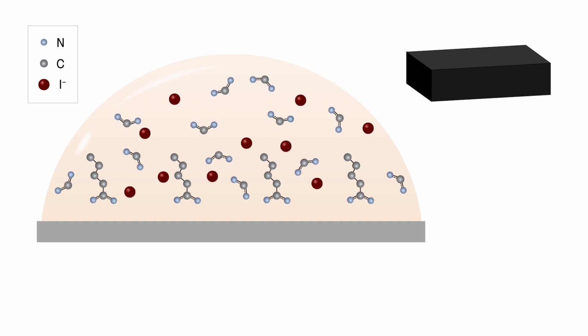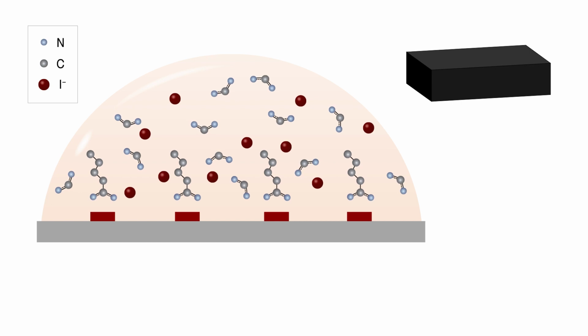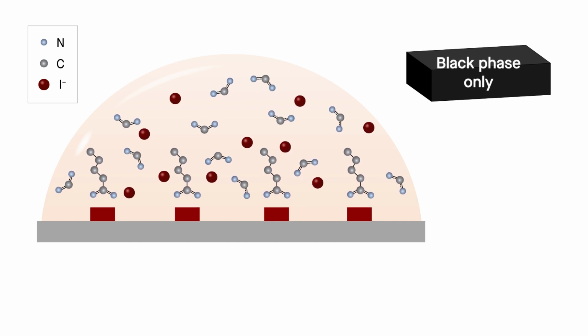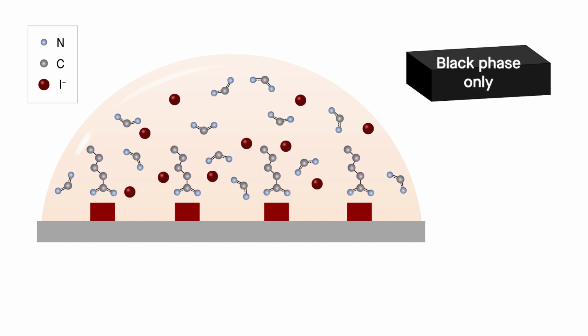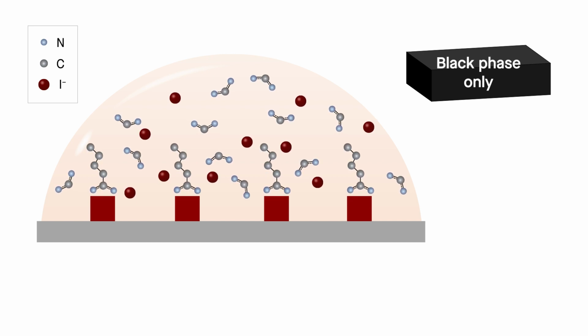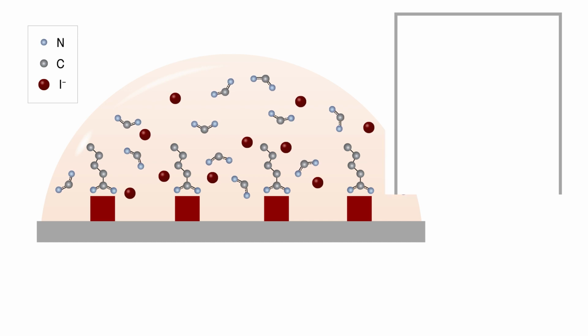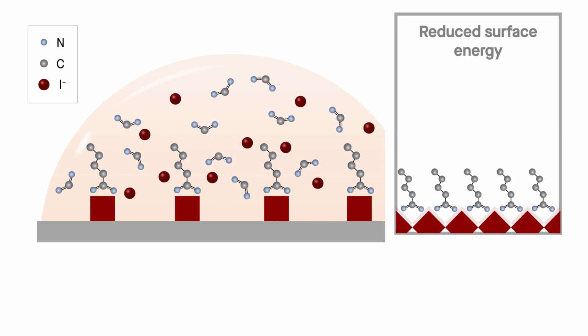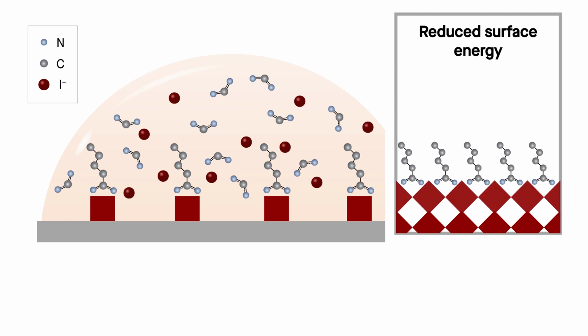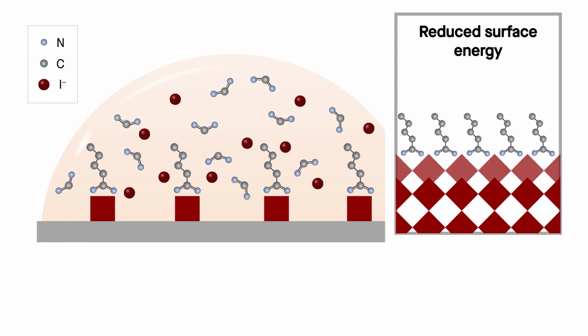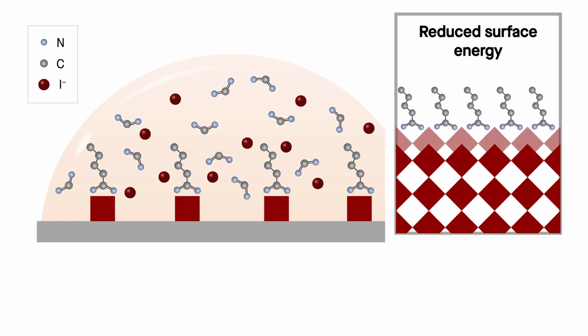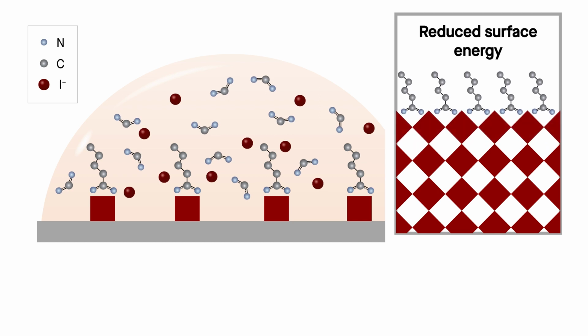Fitted with a polar head and hydrophobic tail, PAD could effectively guide the growth of only the black phase of the perovskite. This it achieved by strongly attaching to a specific face of the black phase crystals. In thermodynamics terms, this attachment lowered the surface energy of a specific plane of the black phase beyond that of any other phase, making it the most likely to grow.